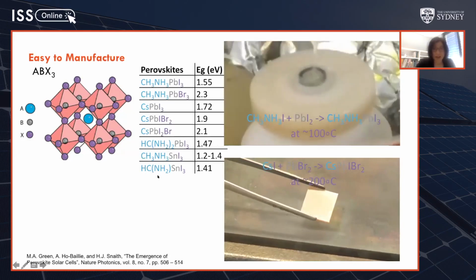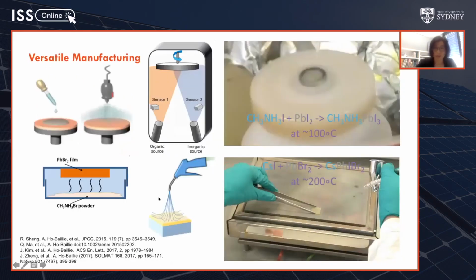Now, in our lab, we just about try every deposition method we can get our hands on. So you can fabricate perovskite film by spraying, or evaporation, meaning you heat the perovskite precursor without any use of solvent, such that the material will evaporate and condense on the cold substrate.